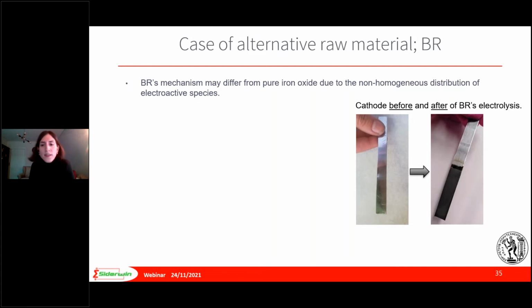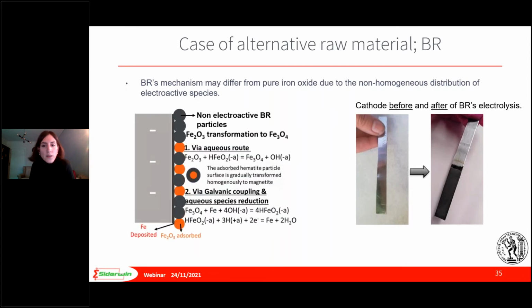These observations lead to the conclusion that the mechanisms of the two raw materials differ a lot. There are strong indications that the non-homogeneous distribution of the electroactive species, meaning the impurities that bauxite residue contains, results in lower current densities. The coverage of the cathode surface with the iron oxide particles is reduced compared to the pure hematite, and thus the current efficiency decreases in this alternative raw material case.